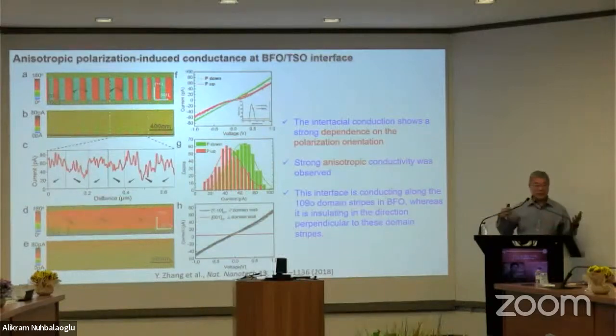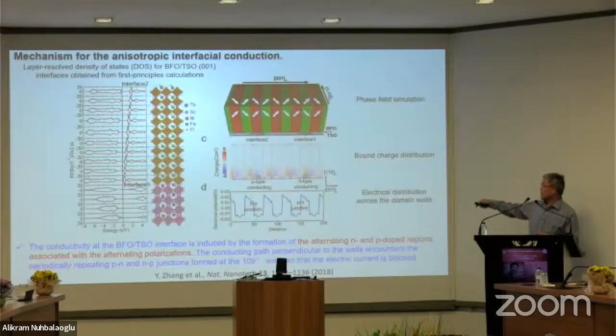So why the conductivity? Conducting is okay. From physics, we understand the ferroelectric interface can be conductive. But alternating is also understandable by a PN junction. When the polarization is pointing downwards, you have an electron gas, and pointing outwards, you have a hole gas. And then the electron and hole conducting regions connect to each other. You will form PN junctions alternating from one to another. So this will be the display here.